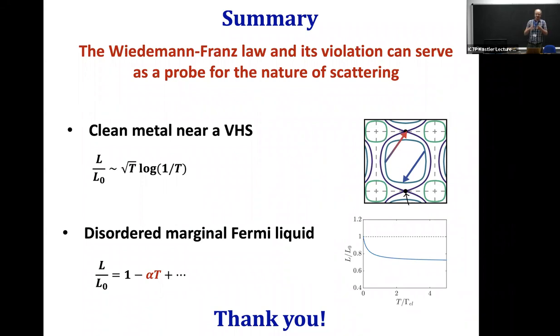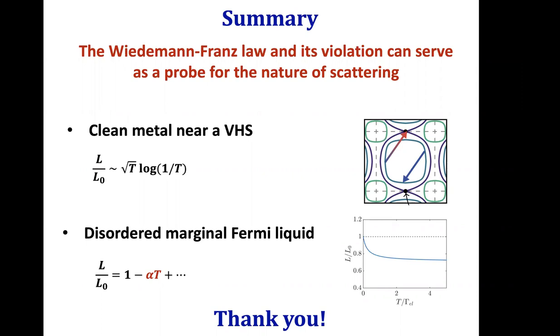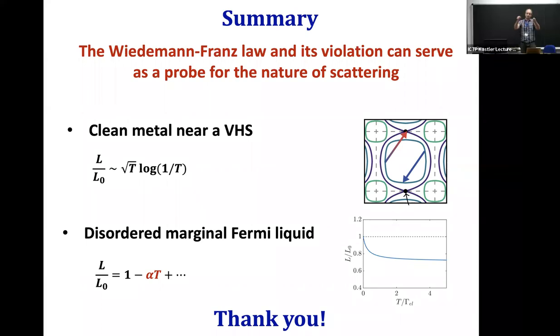So you say the scattering in this model of electrons near the Fermi surface is essentially momentum independent, okay, and T-linear. And that's coming in both to the thermal and to the electrical resistivity, but it's always inelastic. So these scattering processes are weighted differently for the electrical and the thermal resistivity, unlike the elastic case where they're weighted equally. Okay, so if you go to zero temperature, it's all elastic, and then the Lorenz ratio is obeyed. If you look at the first temperature correction, you get a different correction, T-linear, but different for the sigma and the kappa. And that's why if you look at the ratio, you get the linear.